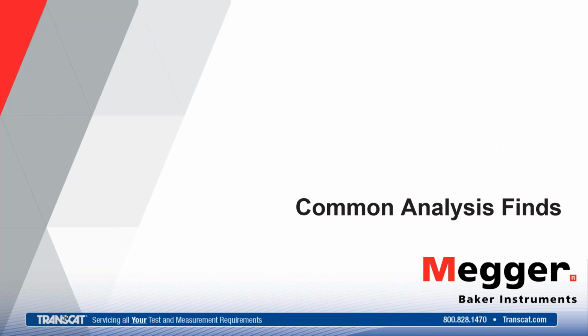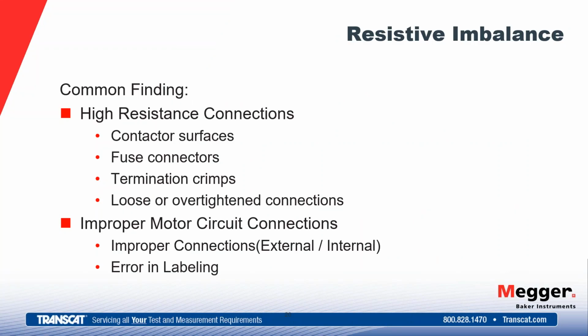So, common analysis of faults, again, resistive imbalance. We're going to look at high resistive connections that can cause imbalanced voltage, imbalanced currents, and higher heating in that motor. High resistive connections can be the contactor surfaces, fuse connectors, termination crimps, loose or over-tightened connections. A lot of times if you're testing switchgear, you get a resistive imbalance, you open up the junction box and water pours out to your feet. That's an indication that you may need to revisit those connections.